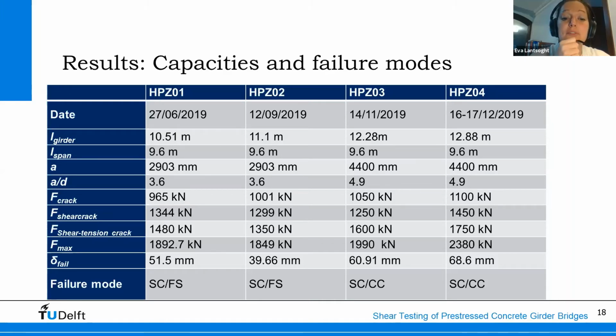And the failure modes that we observed were a combination of shear compression failure with opening of a flexural shear crack in the first two experiments. In the third experiment, we saw local crushing of the concrete in the top flange, as well as shear compression failure. And in the last experiment, we had as well crushing of the compression field.